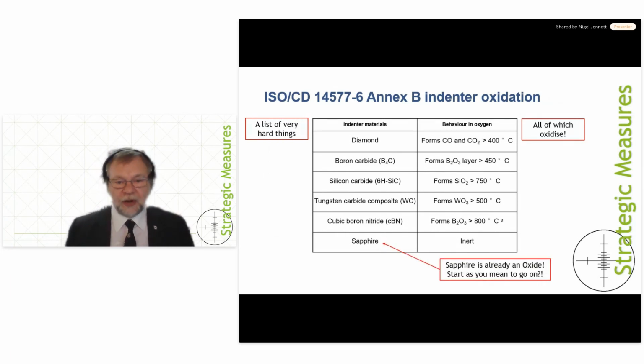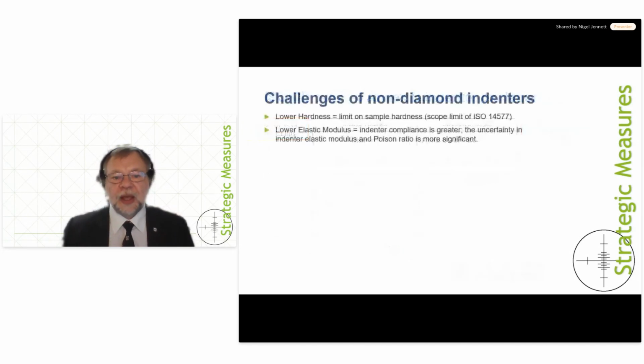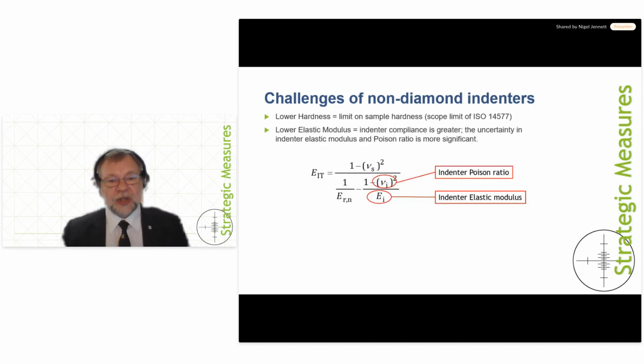Of course, sapphire is already an oxide, and so it doesn't oxidize, and therefore it's a strong contender, if you like, to start as you mean to go on. The difficulty is this, though, that all of those materials are lower modulus and lower hardness, and therefore they place limits on what you can actually test. And the equation that you use to calculate modulus uses the correction for the indenter response, and that's very small for diamond because it's got a high elastic modulus and a low Poisson's ratio, but it's not if you have a normal material like sapphire. And so then you need to know the values for those elastic modulus and Poisson's ratio very accurately, because the uncertainty goes up if you don't.